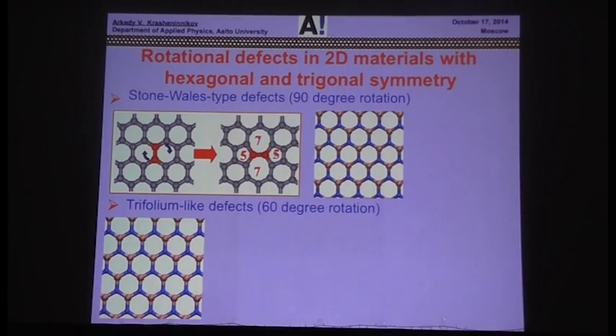Okay, let's go back to Stone-Wales defects. In graphene, it's not a very common defect, it's pretty high in energy, by the way. The concentration is negligible, but under the beam you can create it. Graphene has hexagonal symmetry, but other systems like boron nitride, Dmitry was talking about, and dichalcogenides have trigonal symmetry. So if you rotate two atoms, a 90-degree transformation, you will have homoatomic bonds, which are not energetically favorable. In boron nitride, this will be nitrogen-nitrogen, boron-boron bonds. However, you can do a 60-degree rotation, something like that.